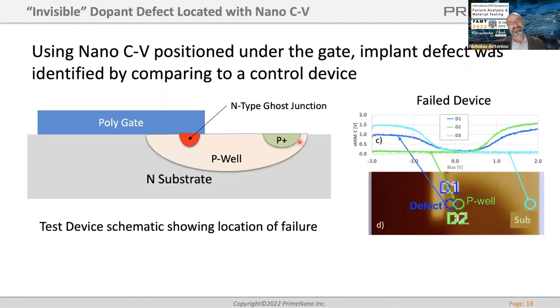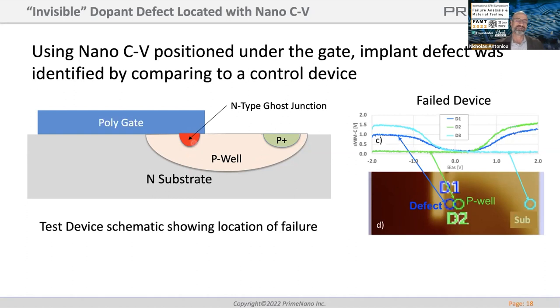Here's an example where there was a defect that was non-visual by normal techniques — SEM or optical microscope. By comparing a known-good device to the failing device and doing nano-CV across this section, we were able to identify an n-type region that wasn't supposed to be there. On the known-good device this didn't exist, but the nano-CV identified an n-type region in the p-well that did not belong there, while the p-type was correct.